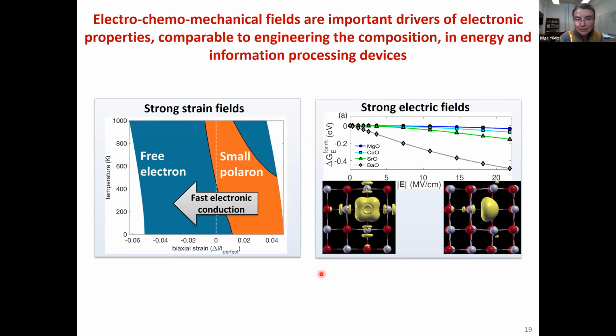Good, so I will end here by repeating that the fields that couple electro-chemo-mechanics, which are not nearly as much studied as traditional composition engineering of the oxide, are in fact important drivers of electronic properties on par with the engineering of the composition, for us to be able to understand the device properties and ultimately to engineer the device properties. As I have shown to you, under strain fields we can change the stability among electronic defects, which have drastically different implications for electronic conductivity. And we can change the stability of different types of ionic defects and their electronic polarization under electric fields, which have implications for energy conversion and electronic devices such as memory systems that I have motivated us to start with.